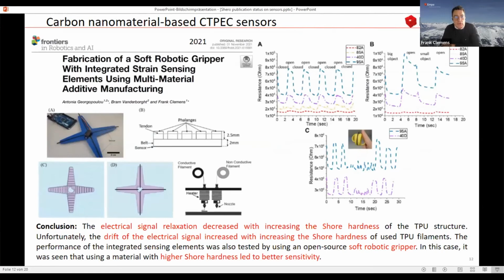Then we started to do the 3D printing of these composites, where we tried to integrate these fiber materials by 3D printing inside a 3D printed structure. For this, we first of all used the TPU material, which is commercially available. And what we also found here again is the same thing. When we had a higher shore hardness of the matrix, we got a better response from the sensor. So the same as we already saw before.